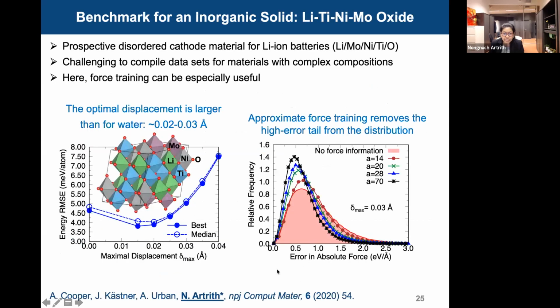I can show you one example of our benchmark. We look at inorganic solid cathode batteries. These compositions have 5 chemical species. Again, this is the rock salt structure. You can see here, we also did the same test. We also tried to find the best distances that we can introduce, and estimate the energies after we have the Taylor expansions. So we see that in the solid structure, introducing 0.02 angstroms and including force information in the training set really also improves our neural potentials.